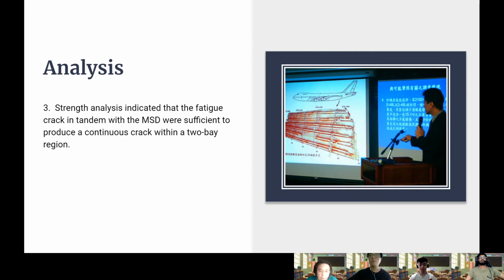The ASC found that a 15.1-inch crack and most of the MSD cracks initiated from the scratching damage associated with the 1980 tail strike incident in Hong Kong, for which the repair was not accomplished in accordance with the Boeing SRM, as the damaged skin in that area was not removed but trimmed and the repair doubler did not extend sufficiently beyond the entire damaged area to restore the structural strength. Prior to the occurrence, the operator's maintenance inspection of B18255 did not detect the ineffective 1980 structure repair and the fatigue cracks that were developing under the repair doubler.